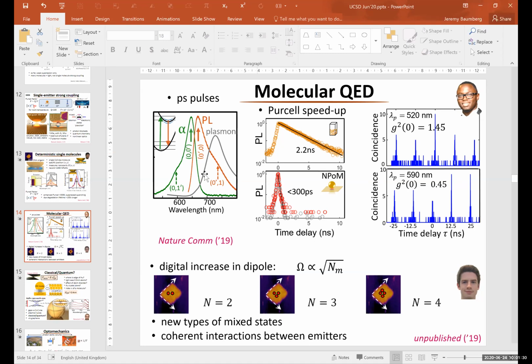Yeah, but so experimentally, what are you getting? Experimentally, what are you observing depending on whether you couple to the absorption or the emission? Here, we're in a system where we were trying not to be in strong coupling. We also can go into strong coupling here, but actually when we're looking at this, we're trying not to go into strong coupling at the moment. We're just on the edge of it. Yes, but then okay, so when you couple, say, to the absorption band versus the emission band, what are the two different behaviors that you see? At the moment, what we're mainly doing is we've looked at the emission in the system and previously looked at the absorption band. So indeed, it's correct.